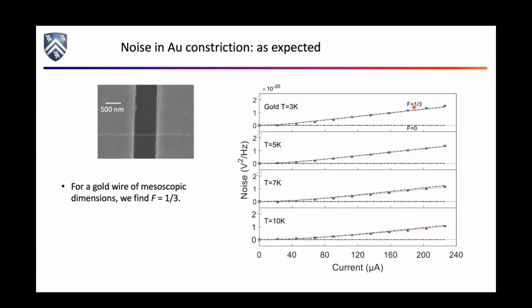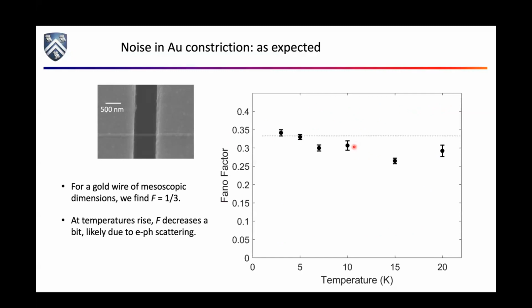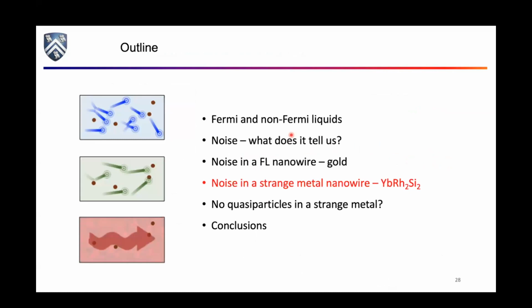So this is what you'd expect if electron-electron scattering is pretty weak in the system, and it works in a very pretty way. If you go to high enough temperatures, and I've got a student where we're going to try and push this to much higher temperatures and see when it really drops off. It starts dropping off because at some point the phonons turn on. The interaction with phonons becomes more important as you get warmer. But even going up to 20K, the Fano factor is pretty close to 1/3. Okay. So what happens if you actually do this in the strange metal?